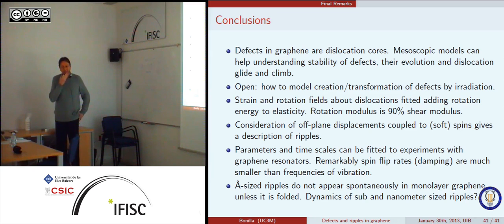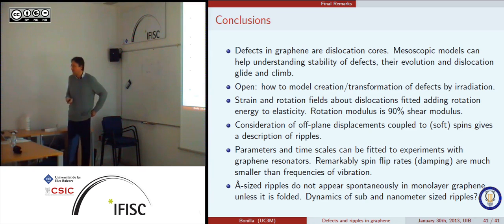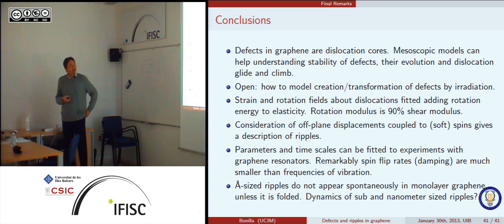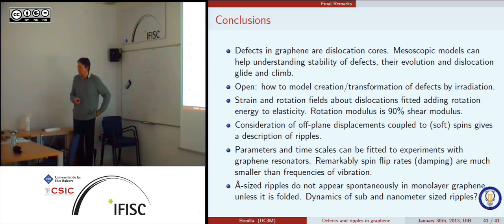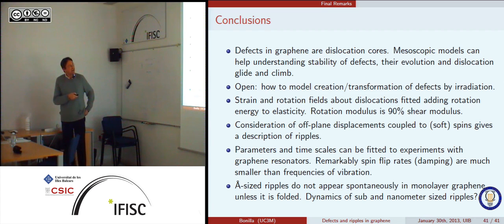I have shown that the defects in graphene are the cause of dislocations. You can analyze them with these mesoscopic models. Of course, we have not put the effects of the microscope into that, but presumably you could do this ad hoc. This is the new part in what we are doing recently. We can explain the strain and rotation fields about a dislocation by just adding to simple elasticity the rotation energy of appropriate size. And then the ripples we just studied with different hard and soft spin models coupled to elasticity. Thank you.